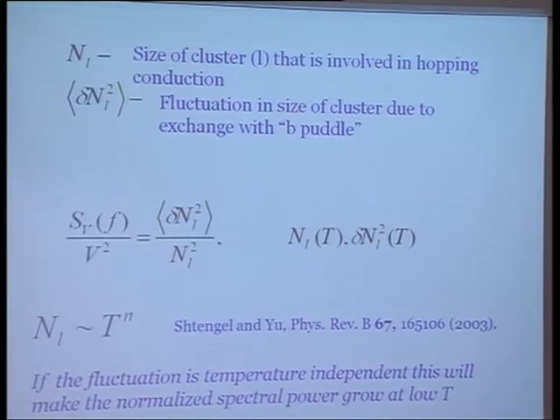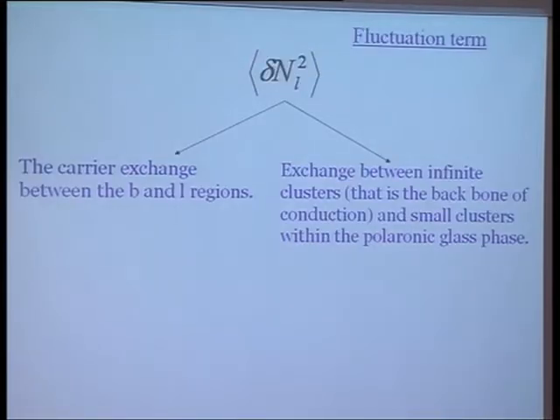What it means is that as you go to higher temperature, you get bigger clusters, and as you go to lower temperature, the cluster size goes down. If that happens, then I should be seeing the noise going up at low temperature. And in many of the percolative systems in which you have hopping conduction, noise does go up at low temperature. But what is also important is that if the fluctuation term doesn't have any temperature dependence, then noise should go up at low temperature. But what happens to this term?